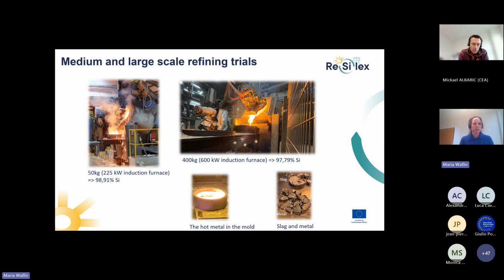And the one we did in 50 kilo, the purest metallurgical grade silicon we got out after this refinery was about 98.91%. And from the large scale, we reached 97.79. And here you can see the tapped metal and also the separated metal and slag at the bottom.